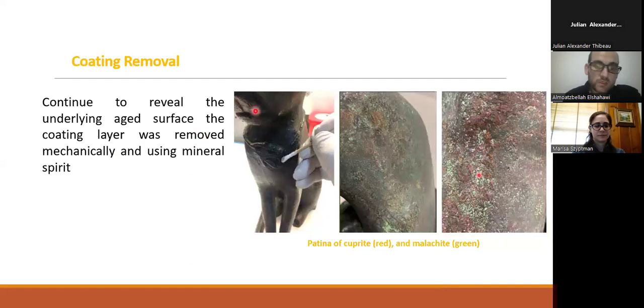Here the surface is very glossy, and here we can see the surface that actually matches the other ancient metal artifacts. The surface appearance was further evened by the application of a coating. Today, this evidence seems inconsistent with a corroded ancient bronze surface and thus somewhat deceiving. We removed a small window, as we can see here from this picture, of the coating with organic solvents and discovered a more characteristically corroded surface beneath, as we can see here. Also, the coating layer was removed, and this revealed the underlying aged surface.